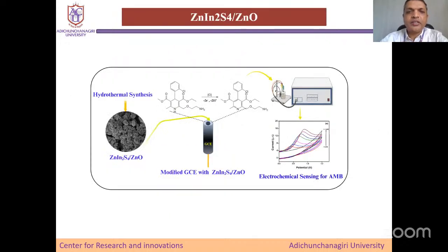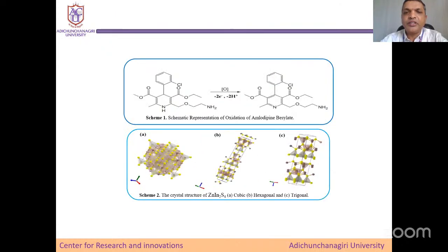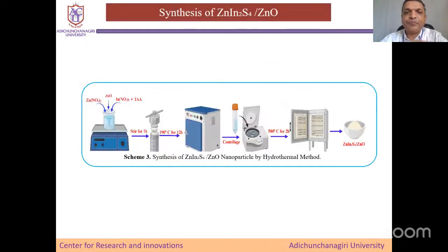And we used an zinc indium sulfide/ZnO nanocomposite on a modified electrode. We just pasted it on the glassy carbon electrode, which was modified, and it was able to sense the amount of amlodipine besylate in the material. So we detected it using an electrochemical sensor. The synthesis is very simple. It is a hydrothermal process. You put all the ingredients, zinc and indium and thioacetamide, together in a reactor and place it in an oven so that we get the nanoparticles.